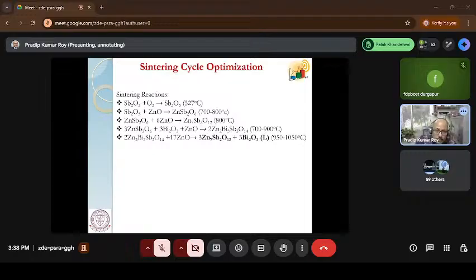So I said there are three phases. One is zinc oxide, which is almost 97% present there. Bismuth oxide, which is in liquid phase, mostly forms around 950 to 1000 degrees Celsius. And the second is the spinel phase. Spinel phase is this one, Zn7Sb2O12. This phase is very much critical, because I need a high dense body. There should not be any kind of leakage.